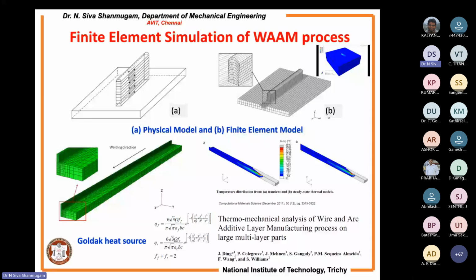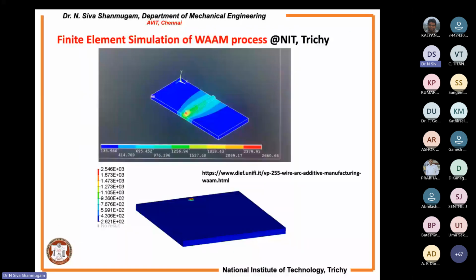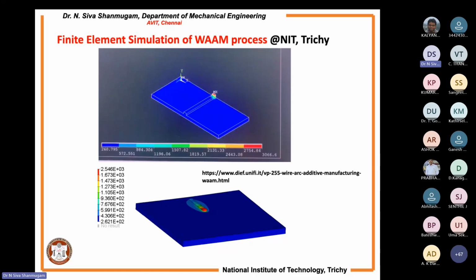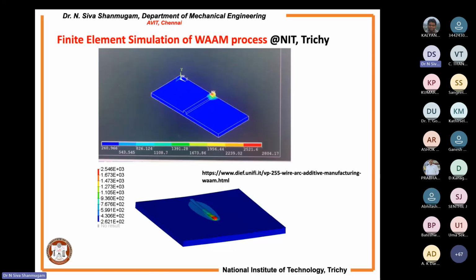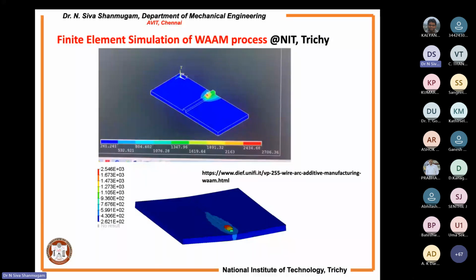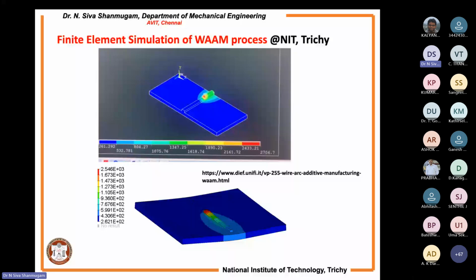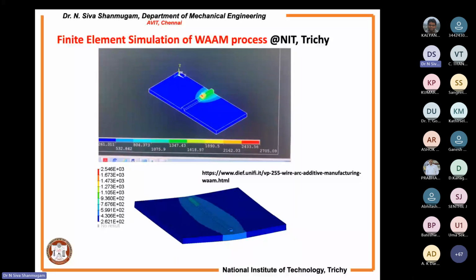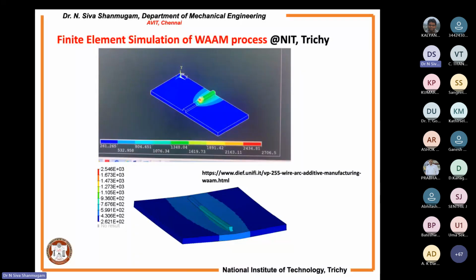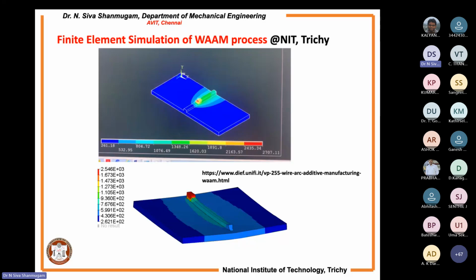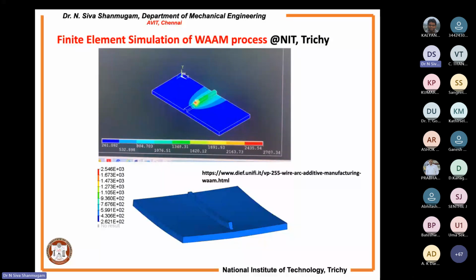So my part, as I'm a finite element simulation man, it is very important to find out the stresses induced in the body. So this is the base literature where we have gathered that information. With the help of this literature, we have simulated. I want to thank my scholar, Dr. Arun Kumar. He made a beautiful analysis, and in the bottom one, you can see the effect of residual stresses on the component. You see there is a big distortion of the material. Once you are laying the material, because of the residual stresses, the entire material is distorted. So this gives the awareness for checking the process parameter and also the deposition strategy. You can predict the temperature distributions, find out the residual stresses followed by the distortions, by doing finite element simulation for changing the process parameter. That is possible only with the virtual platform or by means of numerical simulation packages.